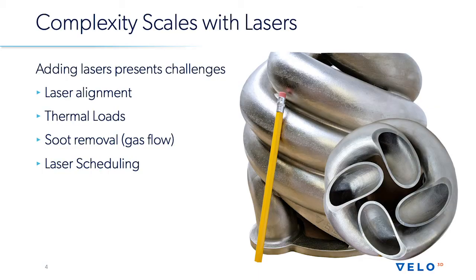Soot removal, so I think it's pretty widely recognized that gas flow is a critical aspect of building good parts in laser powder bed systems. Soot removal when you're melting 4 times as much material is equally critical. You can generate quite a bit more soot, and you have to deal with that. That can be in the filtration system, the gas flow, the inlet and outlet design, but also in the laser scheduling. That's a big part of what you have to consider with multi-laser systems: how to effectively schedule lasers to optimize throughput while still making good material at the end of the day.